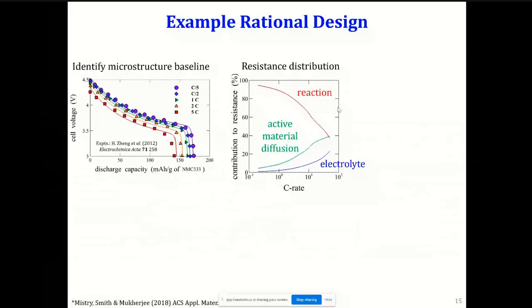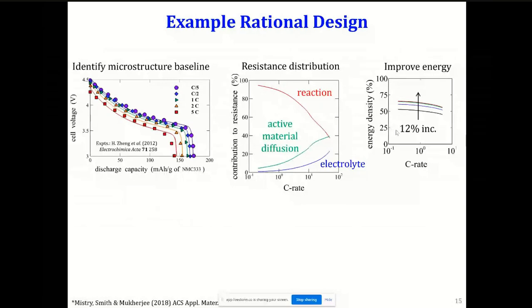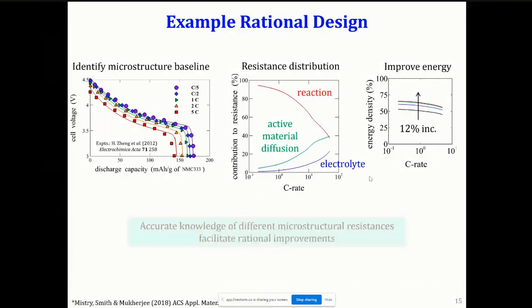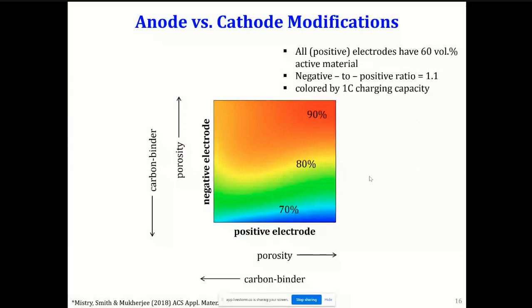get more energy. So as it turns out, after just two of such systematic changes in the design, you increase your energy density by about 12%. And it's across different rates. It's not just increasing at one rate. So having this information about what are the different time scales and what are the different forms of resistances helps you do a systematic design where you carefully, surgically only modify the process that is most detrimental to you. Let me show another example.